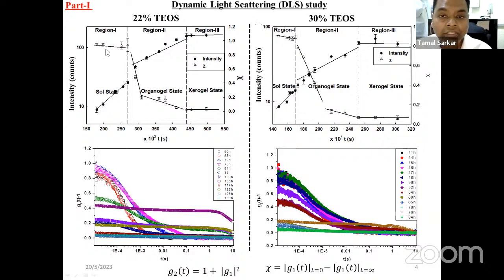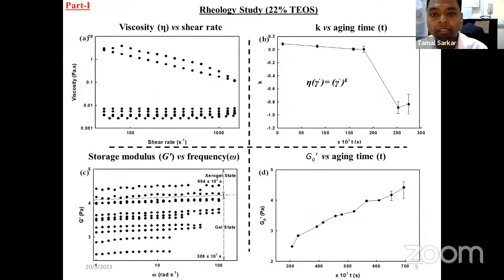That means the gelation has started, and from the gelation point, the chi value drastically decreased to this point and kept on decreasing till it becomes xerogel. Now a similar pattern has also been observed for the case of 30% TEOS, and again the gelation and the xerogelation happened quite earlier. Now a similar phenomenon was observed through rheological study.